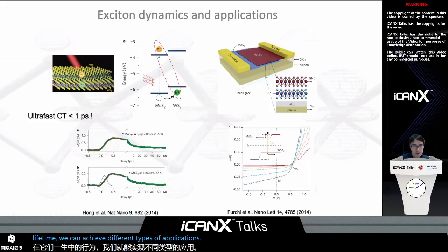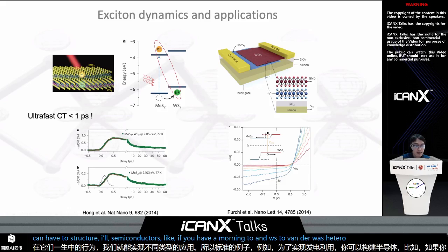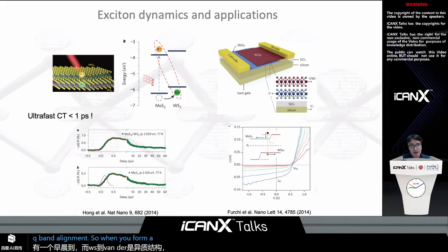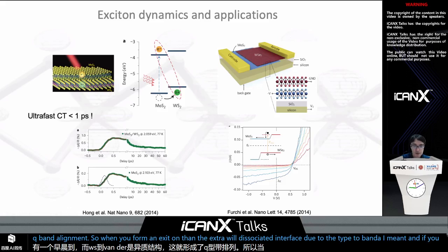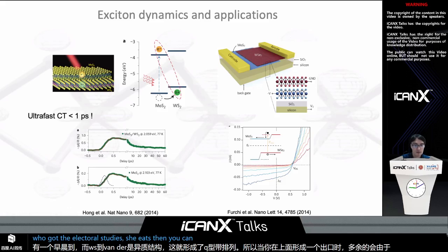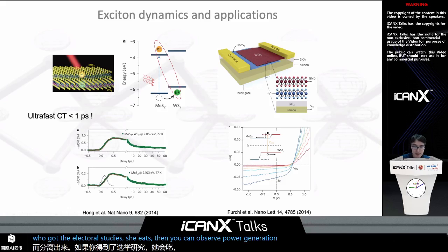One standard example is, for instance, to achieve power generation using a heterostructure of semiconductors. Like if you have a MoS2 and WSe2 van der Waals heterostructure, and this forms a type 2 band alignment. So when you form an exciton, then the exciton will dissociate at the interface due to the type 2 band alignment. And if you hook up electrodes to these sheets, then you can observe power generation, or voltage generated at the interface of the material due to the dissociation.